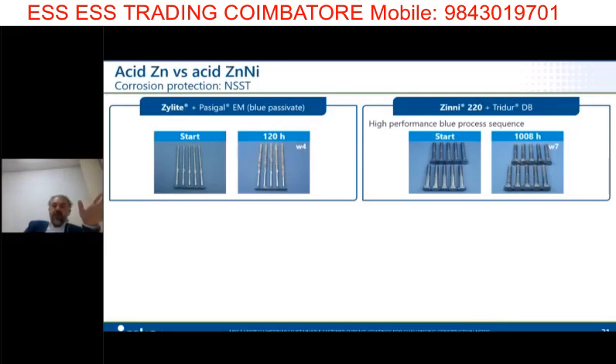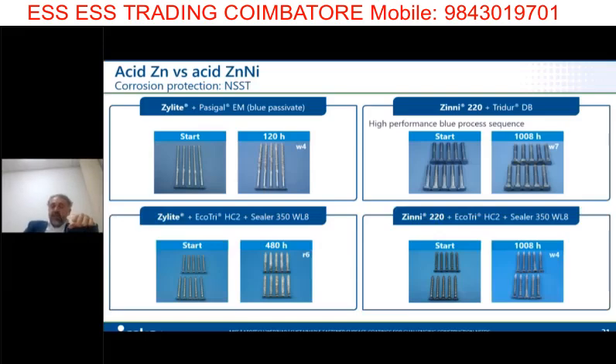In this case, we are comparing zinc passivated parts on the left with acid zinc nickel parts on the right side. In both cases, only passivated. And you can see a big jump: at 120 hours with the zinc, we have W4, which means we can see some white corrosion, while we have a similar situation with the acid zinc nickel, but only at 1008 hours. And this is confirmed also by the second case, where we are comparing zinc and zinc nickel parts with the same post-treatment.